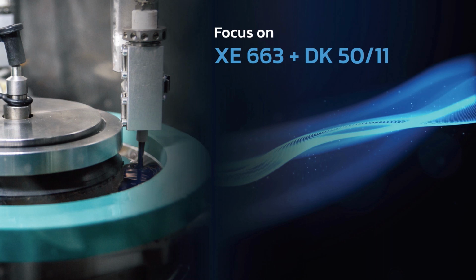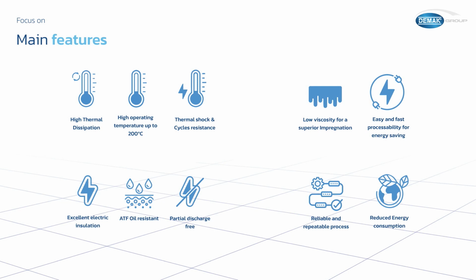As I said, we now focus on a particular system named XE663 and DK50-11. This is a system that shows a lot of good features. First of all, the low viscosity, very important for application and wetting of the motor, of the wires of the motor. High thermal dissipation, high operating temperature, very high thermal shock resistance, incredible how many cycles it resists, resistant to chemicals, for example ATF oil, excellent electrical insulation, and very easy to use and without the need of high temperature for curing.